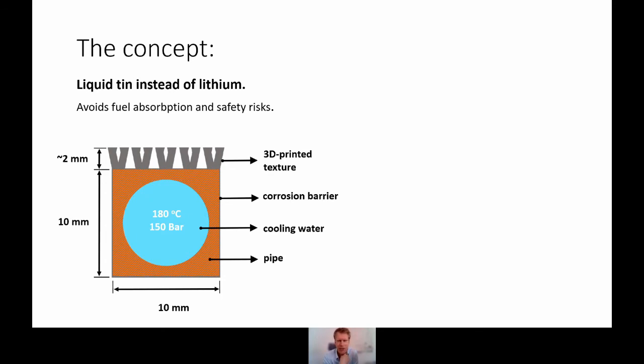There is a square pipe that is round on the inside through which the water is flowing. We have picked 180 degrees Celsius to keep our metal liquid on top, and 150 bars to avoid boiling. And then on top, there is this 3D printed texture. That is where the liquid metal is going to be loaded in. And we can play a bit with the thickness of that layer. So how does it look in a full component?